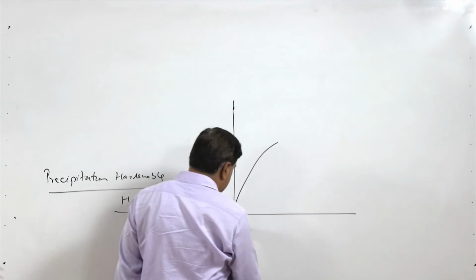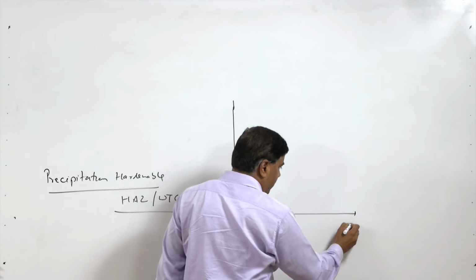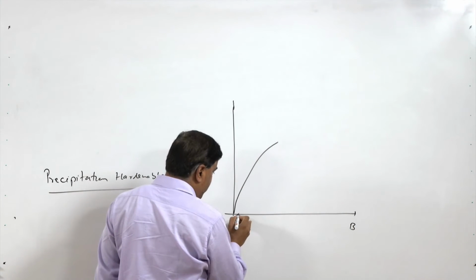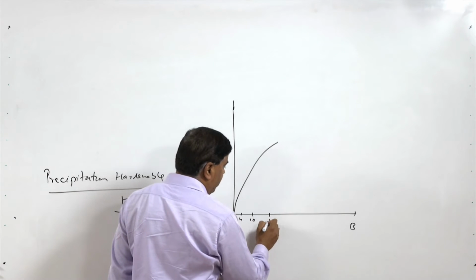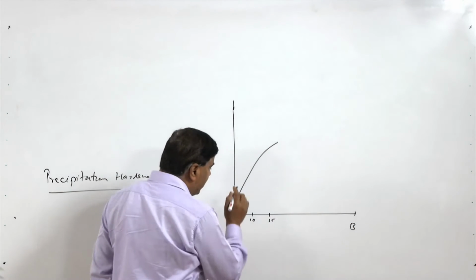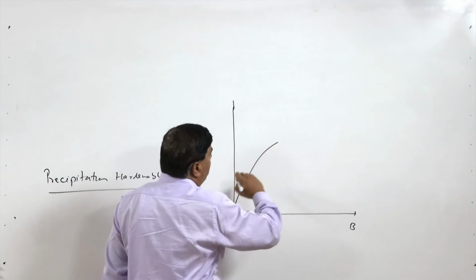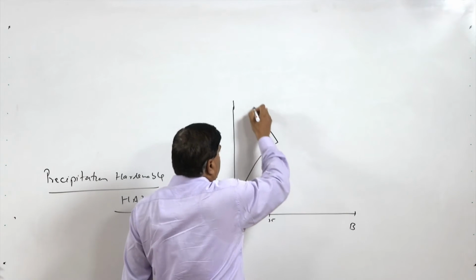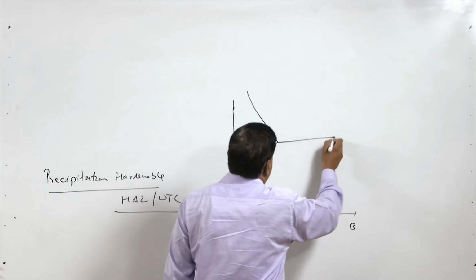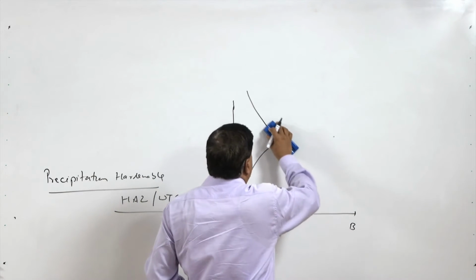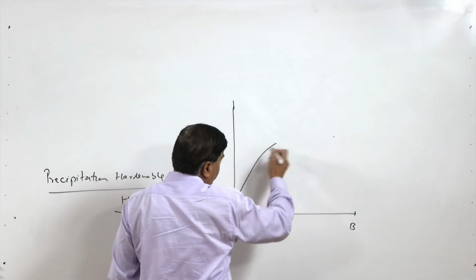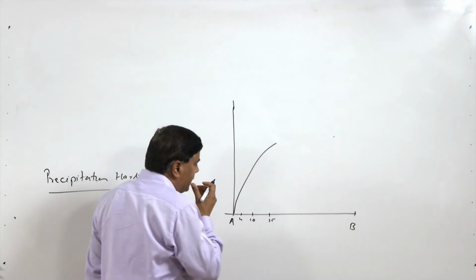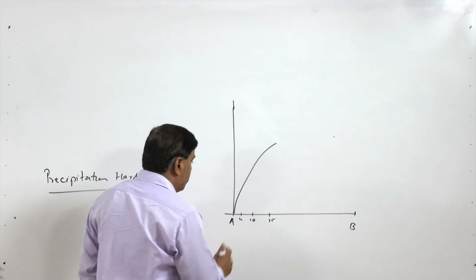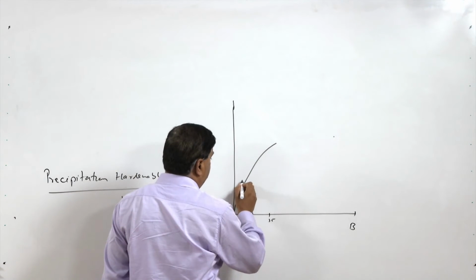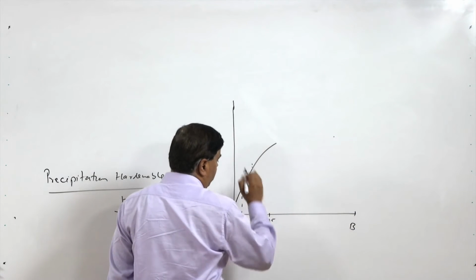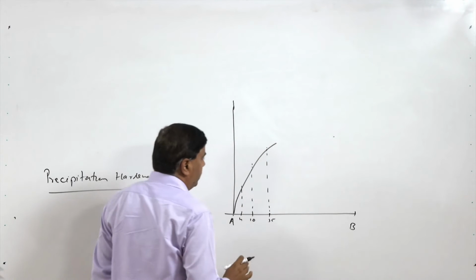So, the alloying elements, say this is the metal A and the metal B, and whenever a particular fraction like say 4, 10, 15 etc., the B is incorporated in A, we will see one particular solvus line, and this solvus line in general is found to be like this. There can be different solvus lines like this, which shows the temperature above which the solute will get dissolved. So, the 4% of the B will get dissolved above this temperature, 10% B will get dissolved above this temperature, and here it will get dissolved above this temperature.